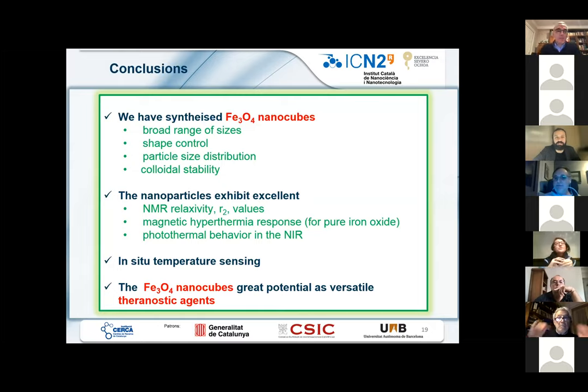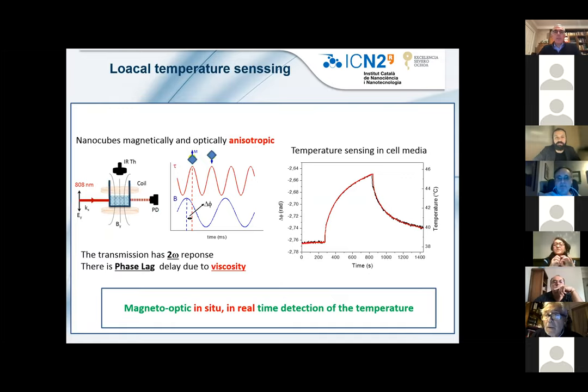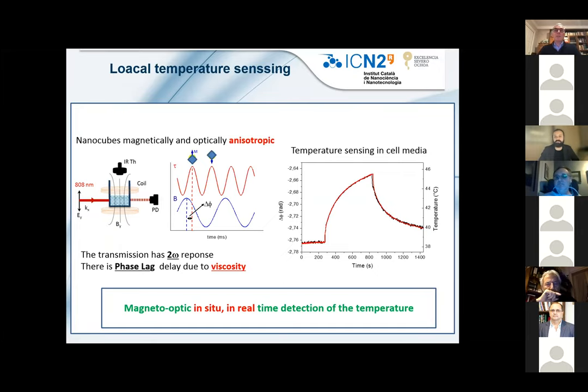Thank you for a nice talk. I have a question concerning the in-situ temperature sensing, the last part of your talk. I clearly understand that viscosity depends on temperature, so if you measure the phase lag, you can correlate this to the temperature. But my question is about the calibration, because everything is strongly dependent on the size of the particle. So how do you calibrate your thermometer in practice? I think you should have very strict control on the size and dispersion of particles in order to get a good calibration for sensing. Does it make sense to you?